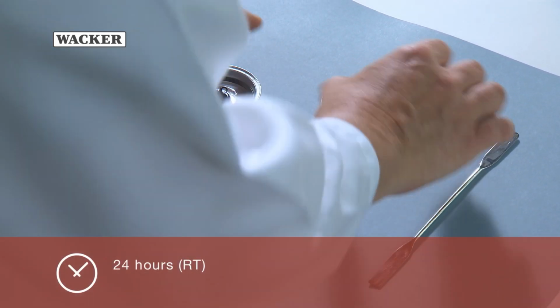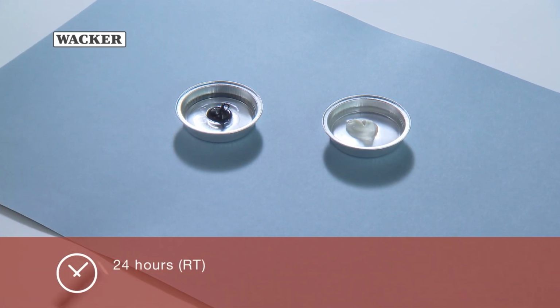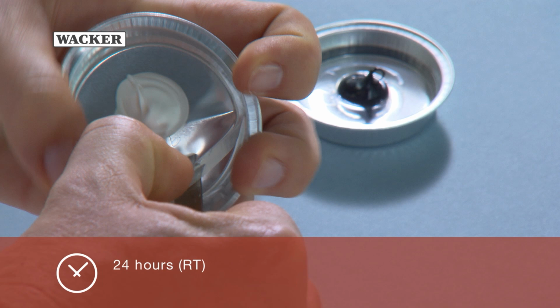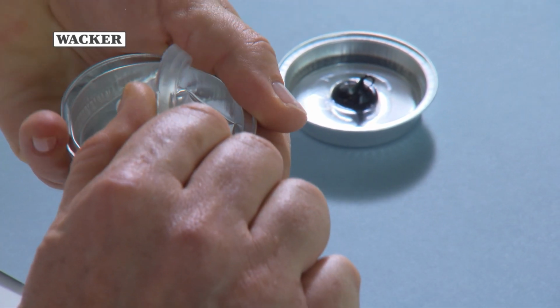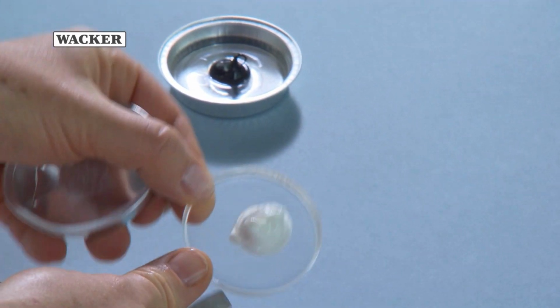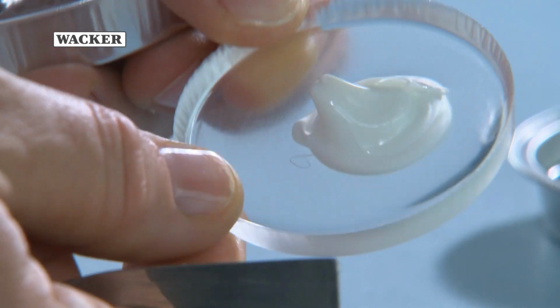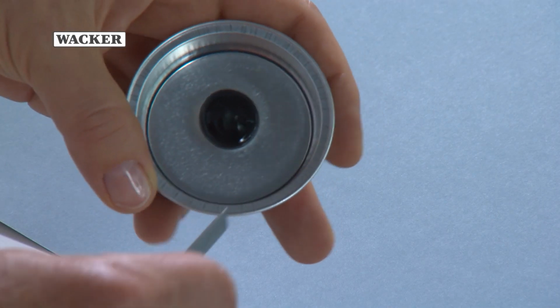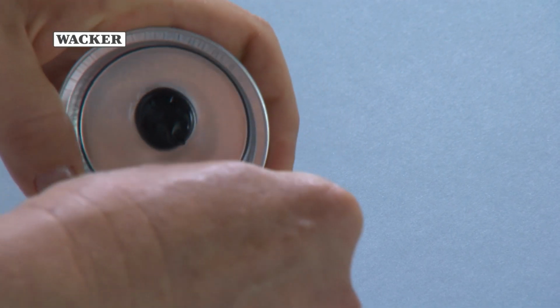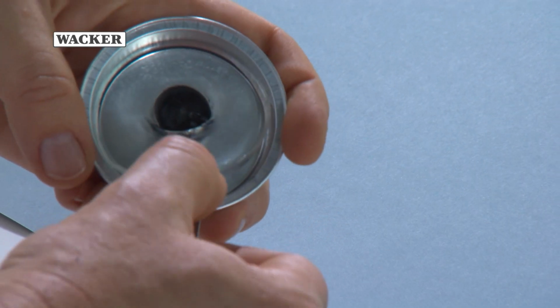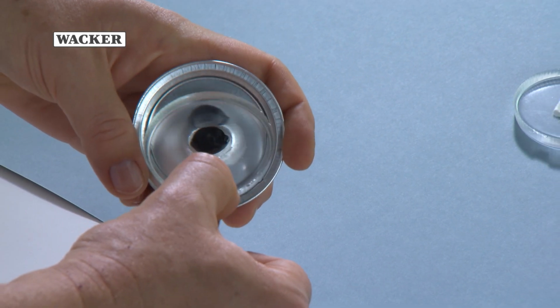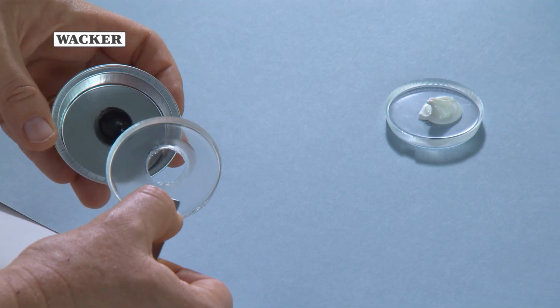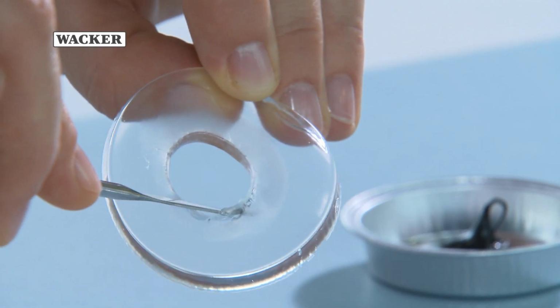This means that an addition silicone like ELASTOSIL RT 601 can be processed along with a platinum-catalyzed grade, such as ELASTOSIL N9111. Combining this with a tin-catalyzed grade, such as ELASTOSIL N189, however, produces the contact inhibition mentioned earlier, as evidenced by a runny, tacky surface.